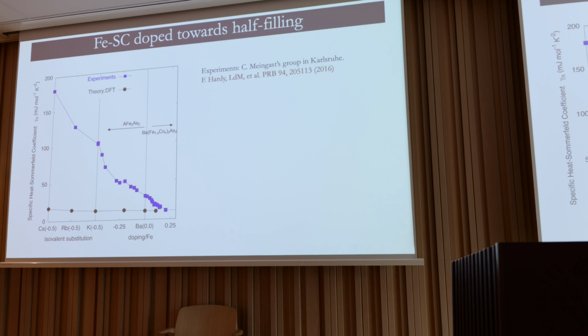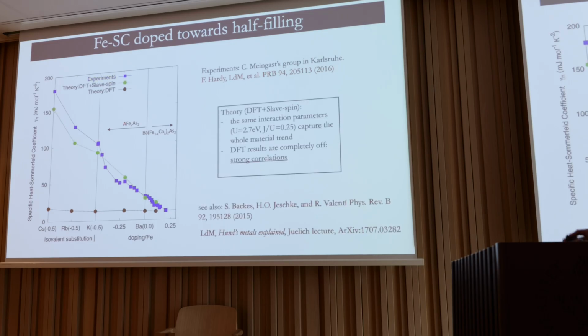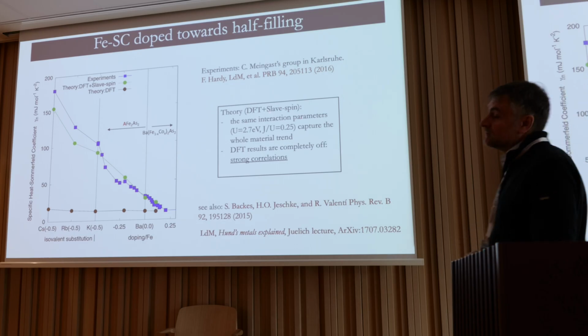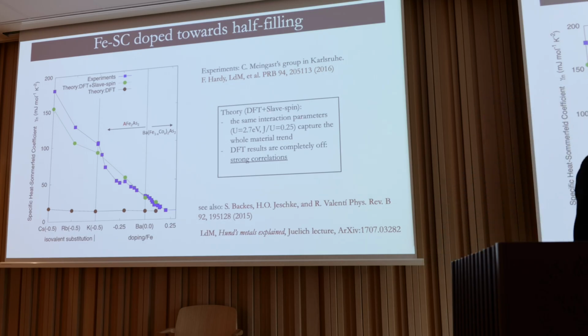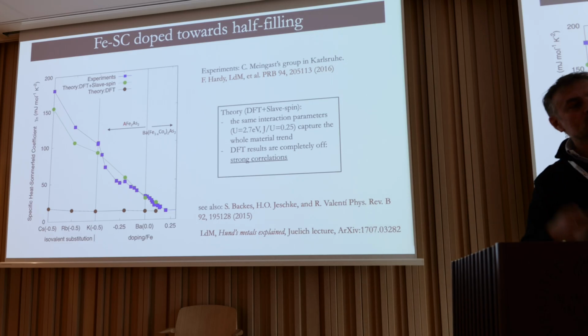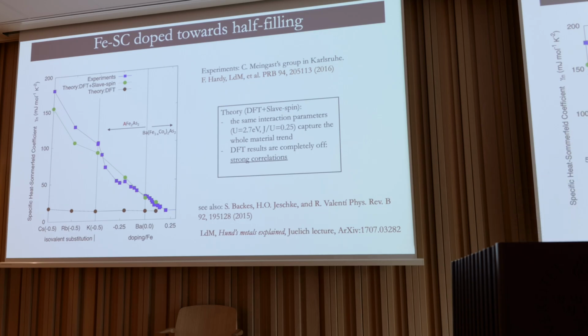Now, what do we do with the theory here? Well, we try to understand what the interactions do, and if we do our DFT plus slave spin or dynamical mean field theory - this slave spin is basically an easy way of doing something that resembles dynamical mean field theory - so if you include the dynamical correlations due to the Coulomb interaction and the Hund's local exchange, you get these green points, which really tell you that this is the physics at play.